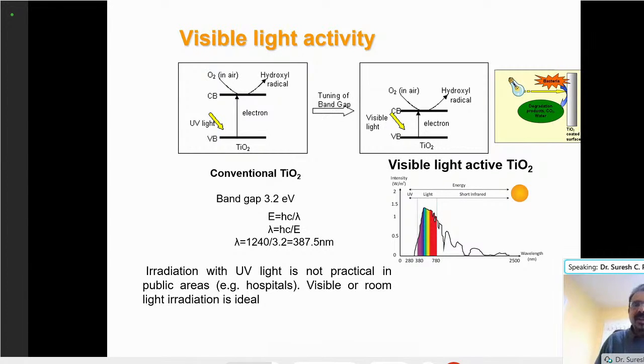The second problem is visible light activity. We discussed that the band gap of titanium dioxide is 3.2 electron volt. Look at the classical equation, E is equal to hc by lambda, where lambda is the wavelength. If you put all the figures there and put the band gap of titanium dioxide, you can see that it's 387.5 nanometer, which means if you want to irradiate the titanium dioxide, you need to use UV light.